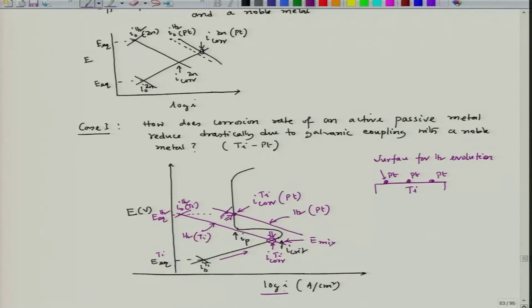So, now the question is, how do we have platinum-enriched regions or local spots on titanium? For that it is a kind of smart move, I would say. We alloy titanium with platinum, and the platinum would be in very less amount. Now this particular alloy, if it is exposed to an electrolyte where titanium can dissolve preferentially, because the titanium is very active compared to platinum.